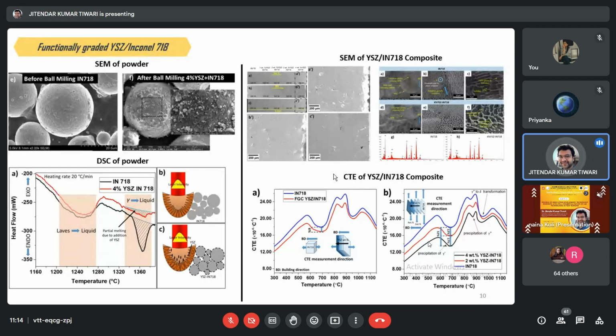vary the laser power, and you must investigate the empirical relationship between the composition and the laser energy density. So you need to develop a relationship. I must say that this particular test is not sufficient. For example, if you are varying the yttria stabilized zirconia up to 10% or 20%, then you must develop an empirical relationship for the variation in the composition. For example 0, 1, 2, 3, 4 and so on, and then you must identify which particular laser energy density is suitable for which kind of composition. That you must understand.